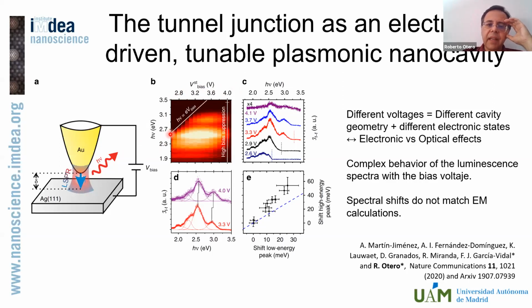So to start with, there's something like an emission threshold. The emission threshold corresponds to the bias voltage that I'm applying. And that kind of makes sense, right? Because the bias voltage separates the occupied states from the unoccupied states. So if you need to couple occupied states in one electrode to unoccupied states in the other electrode, you need one of them to be empty and the other one to be occupied, and that basically limits the maximum energy that you can have.